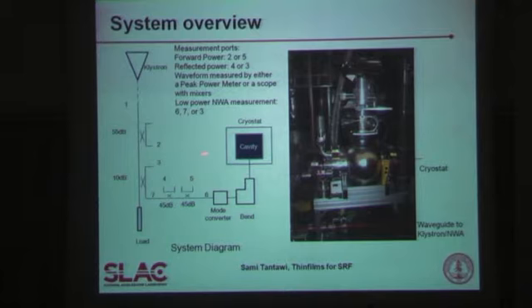The structure of the system is we have this klystron that can produce up to 50 megawatts of power. It goes into a directional coupler to estimate the power, and then it goes into this other directional coupler. It's about 10 dB. We throw away 90% of the power from this klystron, simply to, as much as possible, isolate the cavity from the klystron. As it turns out, because of the huge quality factor of the cavity, we get a huge response, a spike at the beginning when the cavity is charging, that affects the klystron back, and we need to isolate that as much as we possibly can. So this directional coupler does this isolation for us.